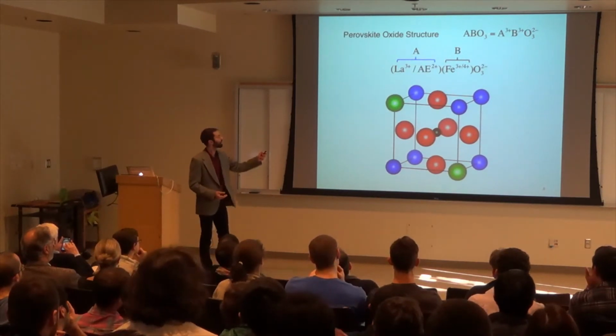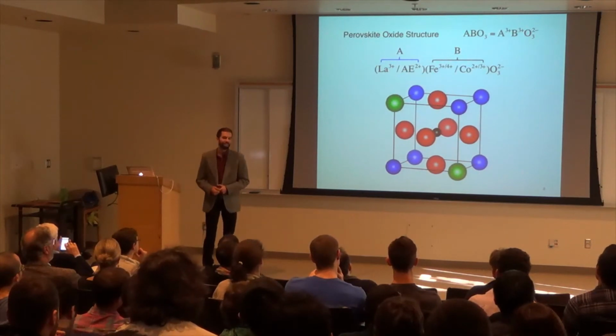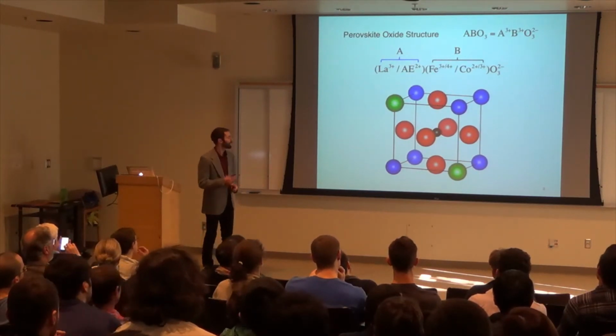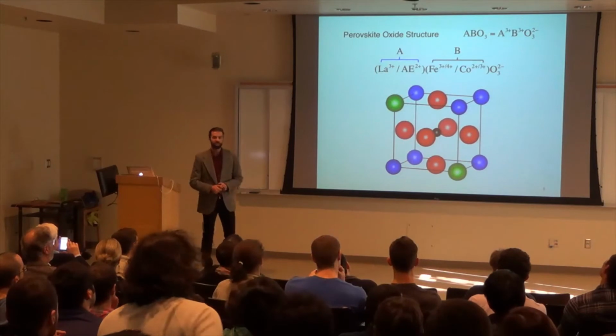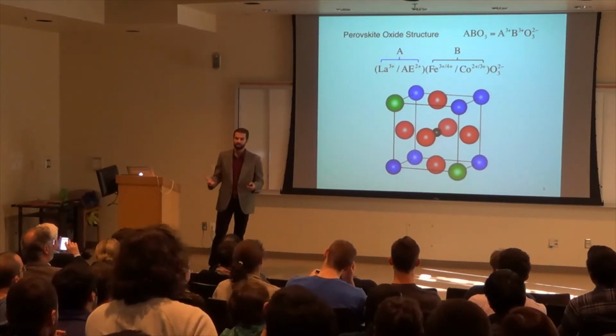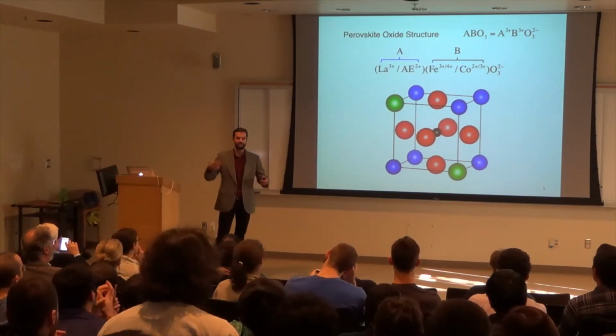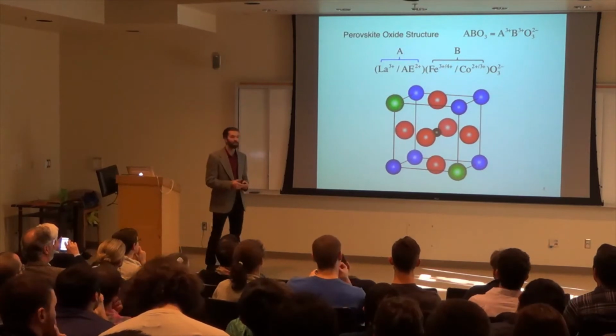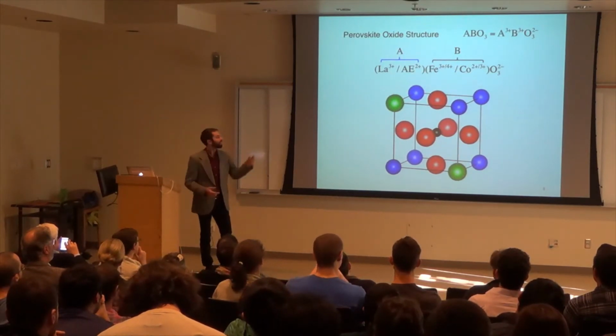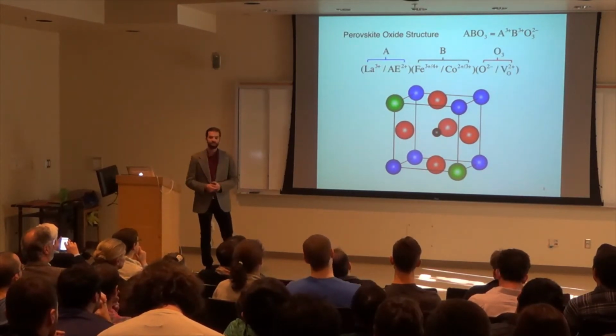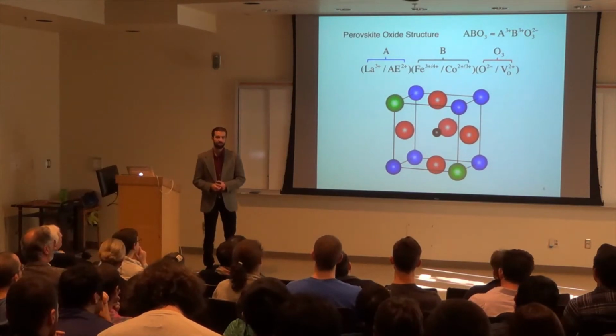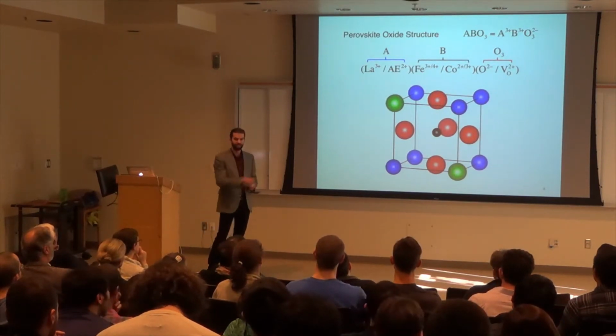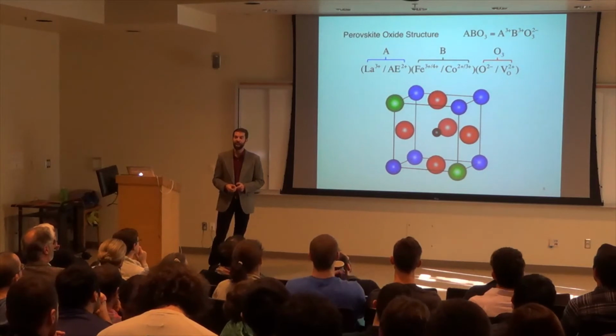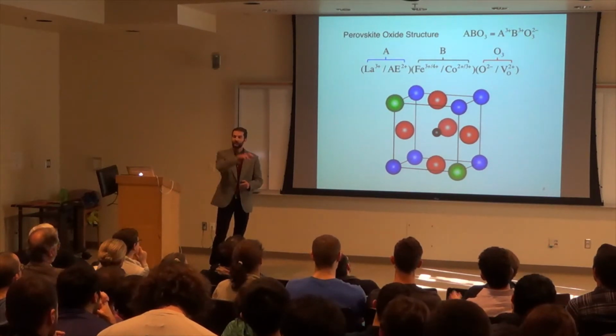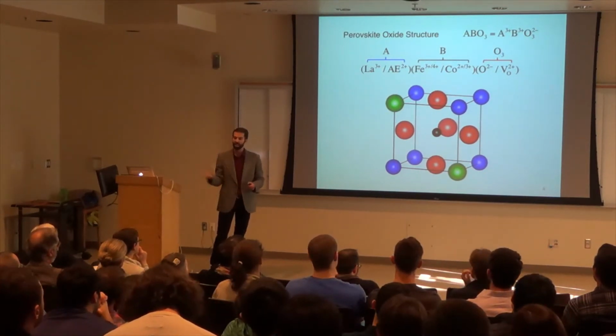Now at the same time that you change the A side, you can change the B side. You can add more different cations. And cobalt actually creates more electronic conductivity. But it also changes the overall charge of the material, and so it must continue to compensate. What it does is create oxygen vacancies. So now oxygen is missing in parts of the lattice. And what this gives the material is ionic conductivity. So now oxygen can incorporate into the material at the same time that you're getting electronic conductivity.